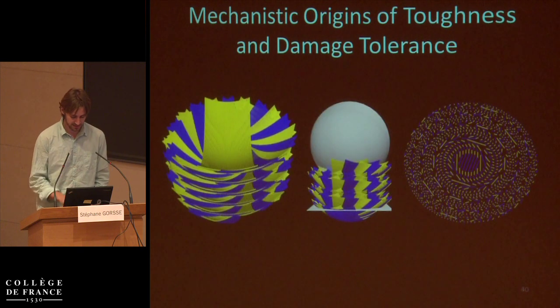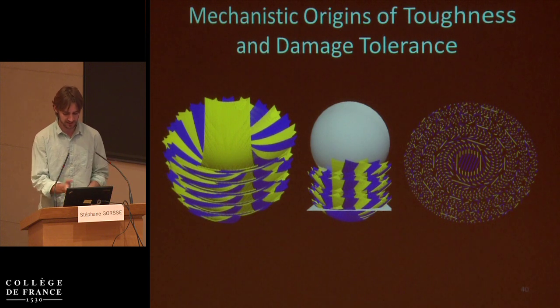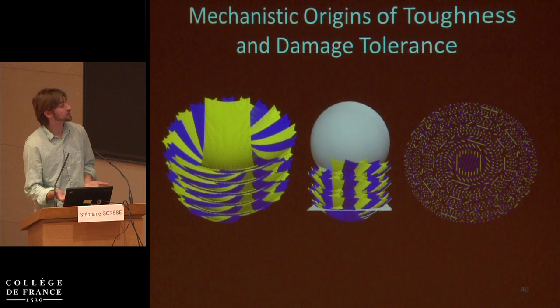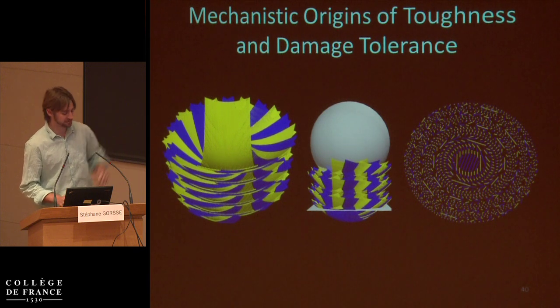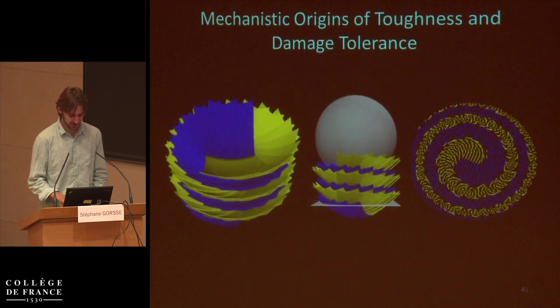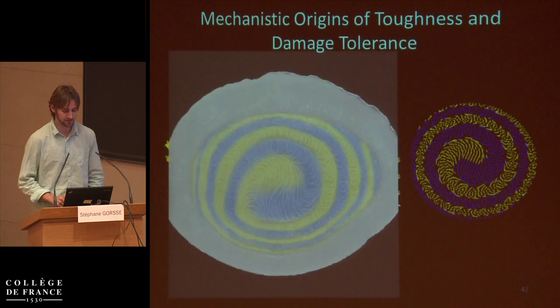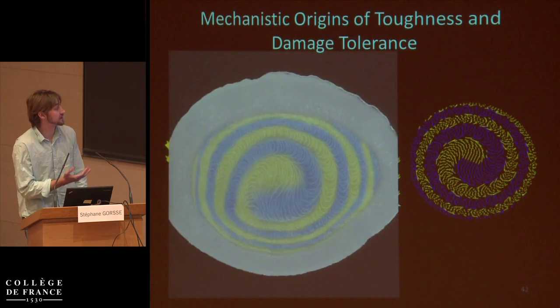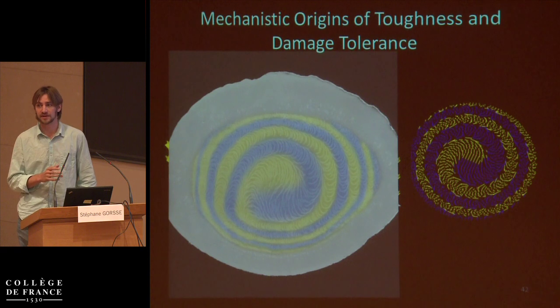But we can make sense of this by taking a rotated helicoidal architecture, curving it around a surface, and then again, now we get the onion that we would expect if we alternate the color of every ring. But if we change our color scheme, then we can completely reproduce the pattern that we found in the club. And the takeaway here is that